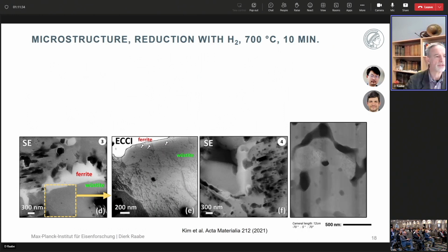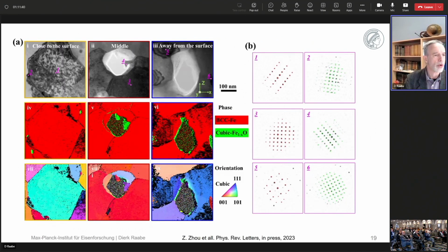We went deeper into the analysis of the porosity. This is just one example where you can see a set of pores, and those were closed pores. Now they have been illuminated here by local diffraction experiments in the STEM so that you can see the phase contrast.